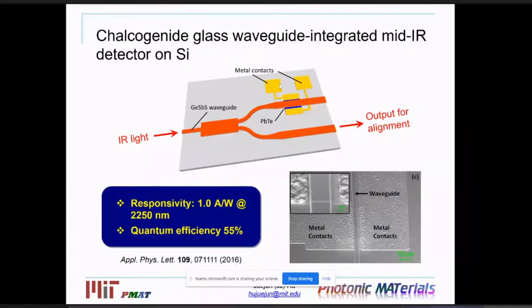This is made out of another chalcogenide material, lead telluride. In this case, the lead telluride is a nanocrystalline material. It also has some unique characteristics, whereby the grain boundary is inherently passivated. So even though it's a polycrystalline material, it does not compromise its photodetection performance. And because it's a polycrystalline material, it can be directly deposited on top of any kind of substrate to facilitate monolithic integration with our chalcogenide waveguide sensors.